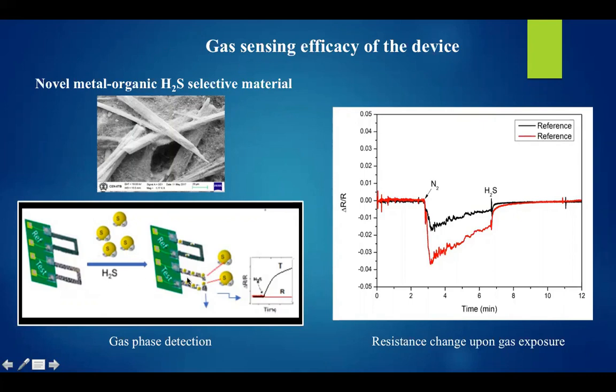the test cantilever, because of the selective material, shows adsorption of this analyte over the surface, and there is a differential stress generated between the top and bottom surface of the cantilever. The test cantilever in presence of analyte bends because of the differential stress, and that in turn changes the resistance of the piezo material. One can see the change in resistance with time, and the sensing of the analyte is done in this way for the piezoresistive microcantilever based sensors.